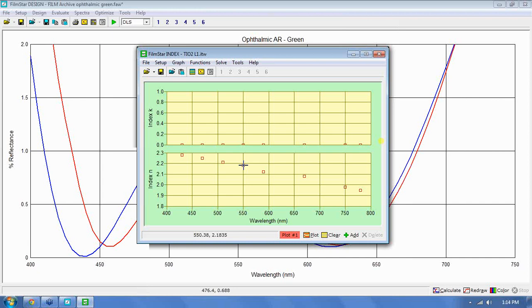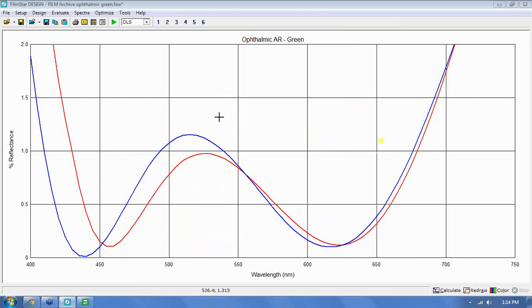And so by looking at these two examples of TiO2 and just those small differences in refractive index, that's where we can see, using the same physical thicknesses, the same process in those different machines, that that's the difference we're actually seeing. If we make our design for machine L1 using the refractive index of TiO2 from that, we can go ahead and take the refractive index and the process parameters for machine L2 and implement it and make our design, make our processes so that they actually match each other, and so that both machines are making the exact same product, although the process might be slightly different, and they would have to be slightly different based on the characterizations of those two different machines. Okay? Any questions about the index data and the characterizations about different machines?